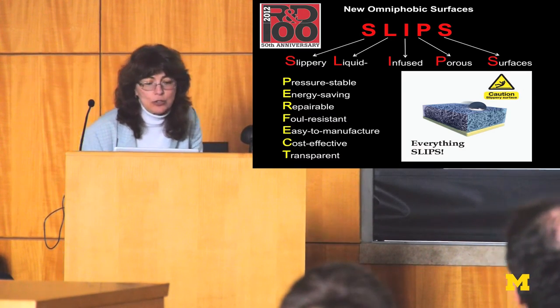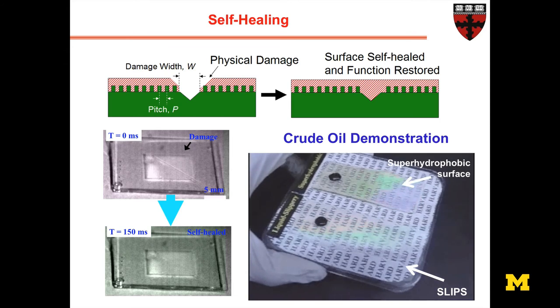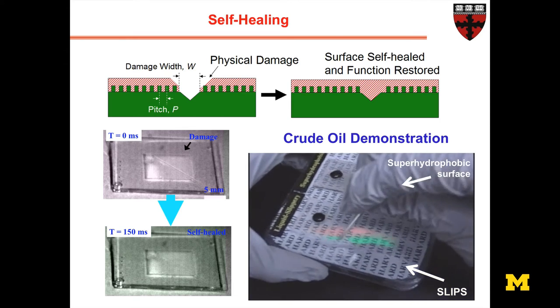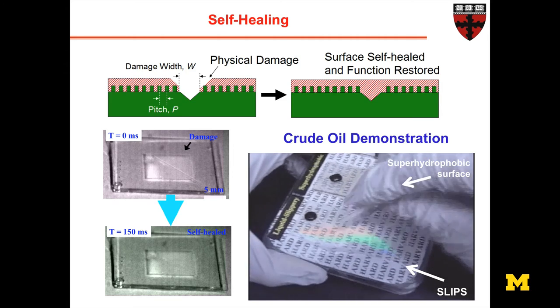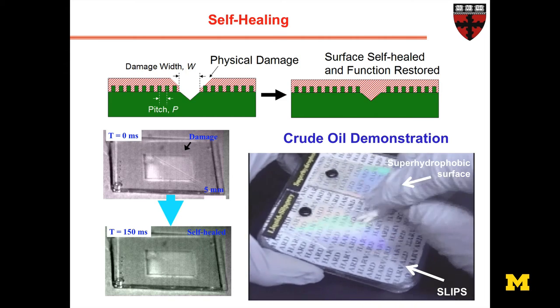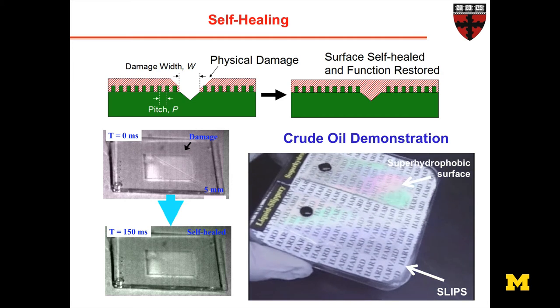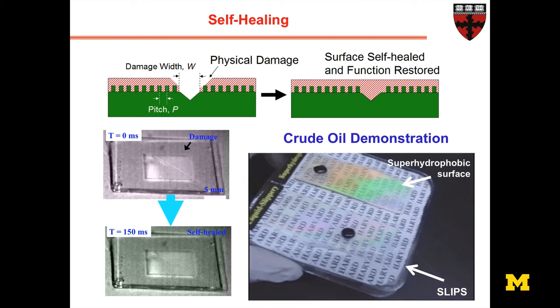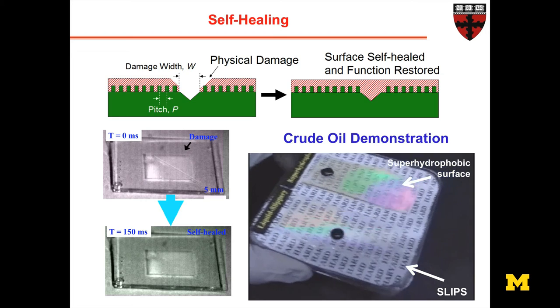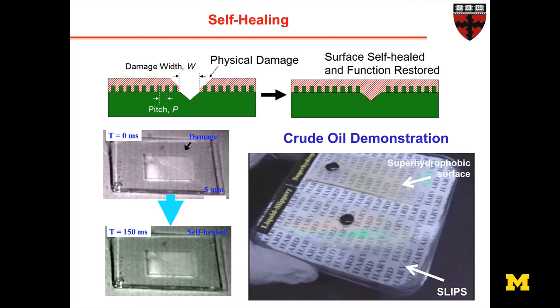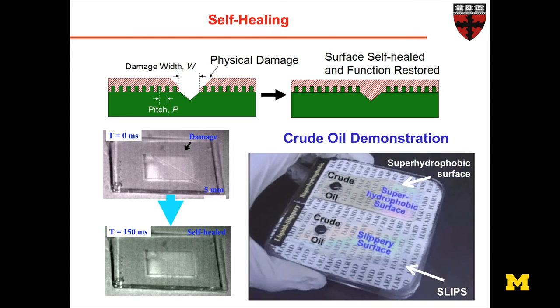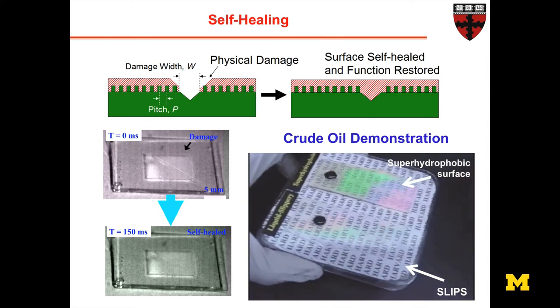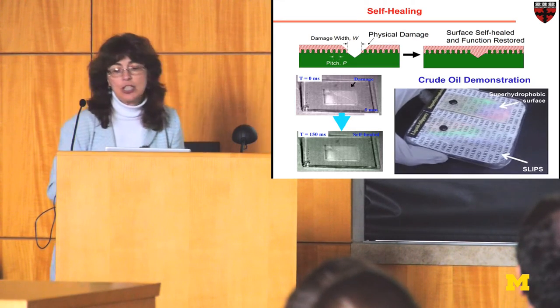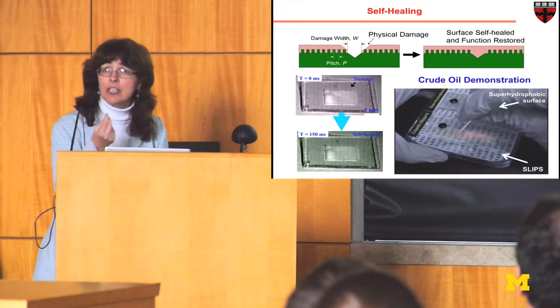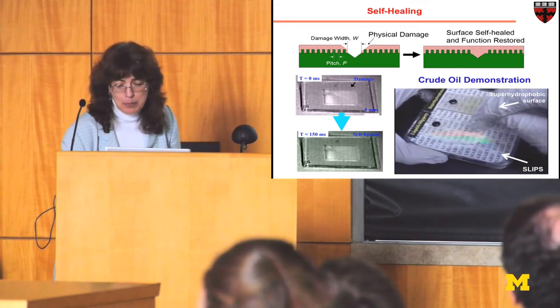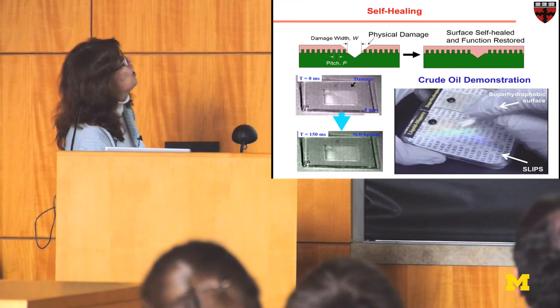So today I will just show a couple of movies where this is really different from other approaches, and in particular, the ability to form substrates that have the ability to self-heal. So here is a super hydrophobic surface, this is crude oil, it's not even moving. Here is a slippery surface, and it was cut in pieces, and immediately the droplet starts to move around. I love oil, not only because it's challenging, but also because it's black and it's very easy to see if there are defects. But it's beyond the ability of self-healing.